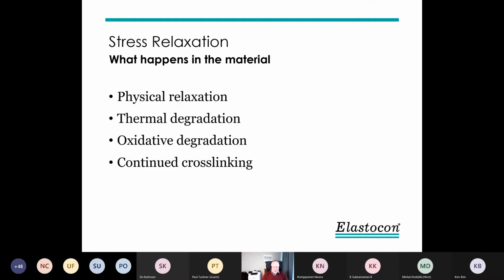And the chemical degradation is mainly then that the molecules get shorter. They are by thermal aging, oxidative aging. And it corresponds quite well if you do tensile tests and look at the elongation at break. The elongation at break during, if you age some rubber material different times, it always goes down, become lower, and that reflects the shorter molecular weight of the material.